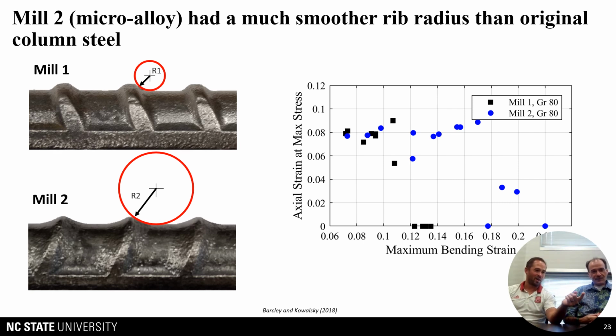And what we saw, the blue is the one with the much higher radius at the base of the rib, because if you go back to that Restrepo image with the micro crack at the base of the rib, you think if that's subjected to compression, a more refined stress concentration would lead to more of those cracks, and that's what we saw when we ran these through the buckle bar tension test. So it made quite a difference, right? The bending strain capacity increased to 16, 17, 18%, and both of these are grade 80 steel.